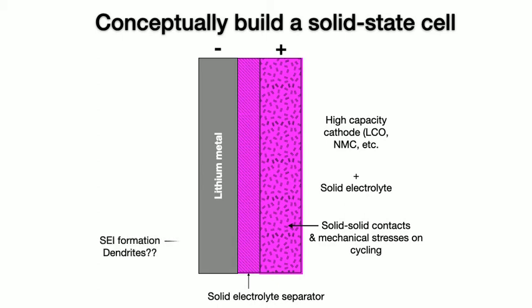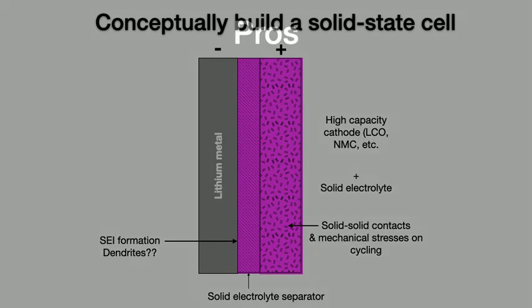So that is tricky. And on the lithium side, just by going to solid state does not guarantee that you won't have dendrites. Dendrites are these needle-like projections that penetrate the electrolyte and can lead to a direct short circuit, and a failure of the battery. So we certainly don't want that. So all of these issues have to be addressed.